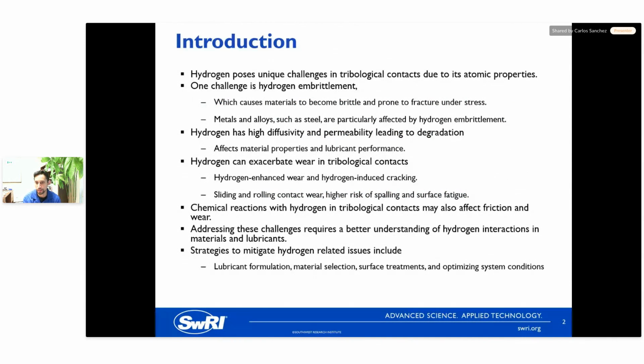As far as tribology goes, it can exacerbate wear, increase friction, or affect frictional performance, have enhanced wear behavior, and also induce the cracking I mentioned earlier. In sliding and rolling contacts, such as rolling element bearings, you have a higher risk of spalling and surface fatigue. So any kind of sliding and rolling contact is one thing to be aware of in a hydrogen case. Of course, you'll also have chemical reactions with hydrogen, depending on what materials are interacting with it. It can also affect friction and wear.